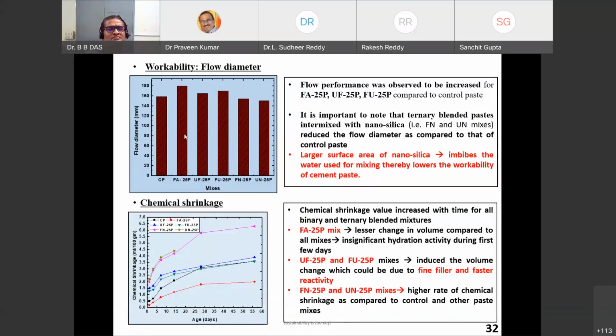Then workability. As compared to control, we know fly ash and ultrafine fly ash increase the workability. But when we started using nanoparticles, we could not do that. These are the flow values we matched by adding a superplasticizer, polycarboxylic ether based. That is necessary. You cannot work with nanoparticles without a superplasticizer.